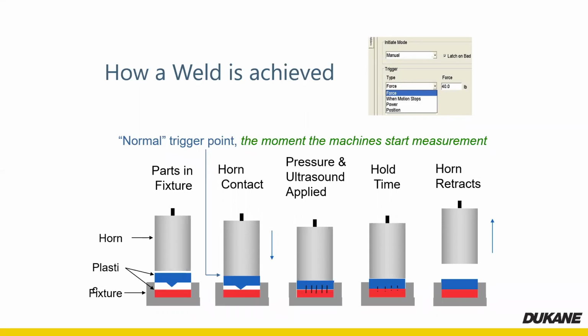The horn comes down and makes contact with the parts. After some amount of force, and in this instance we've got 40 pounds of force set as the trigger force, that's when the ultrasound is turned on and when we start counting, whether it's counting by distance, by how much energy goes into the part, or by how much time we're on the part. We start our count from that trigger point, okay?